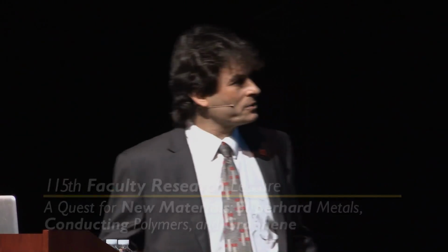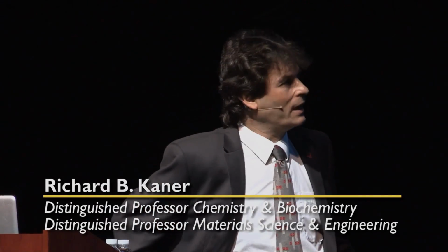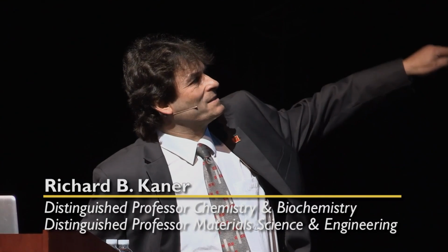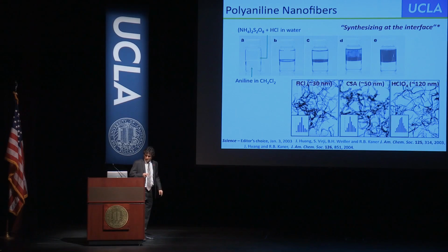And we looked under microscopes, and we have some really good microscopes in our Nano Institute. What we see, by transmission electron microscope, is nanofibers that are about a micron in length and 30 nanometers in diameter. And if we change the acid, HCl is 30 nanometers, camphor sulfonic acid about 50 nanometer diameter fibers, and perchloric acid about 120 nanometer fibers.